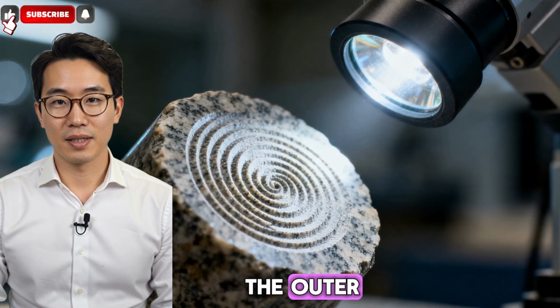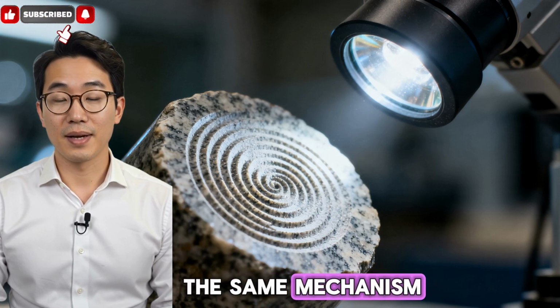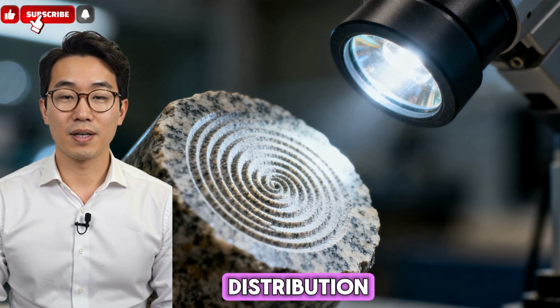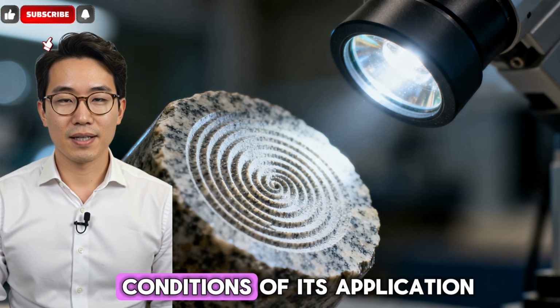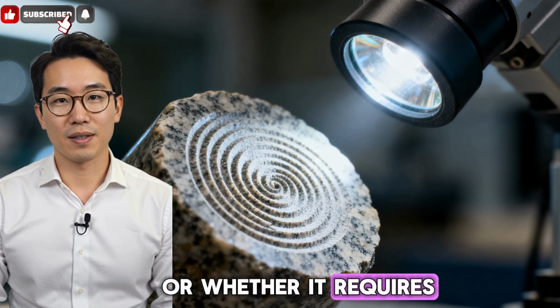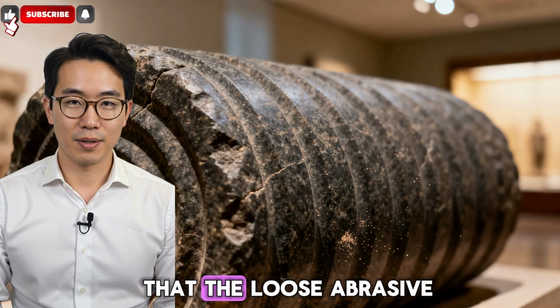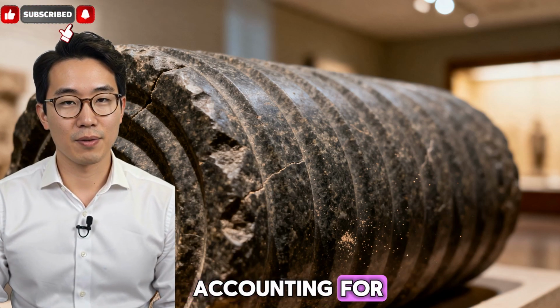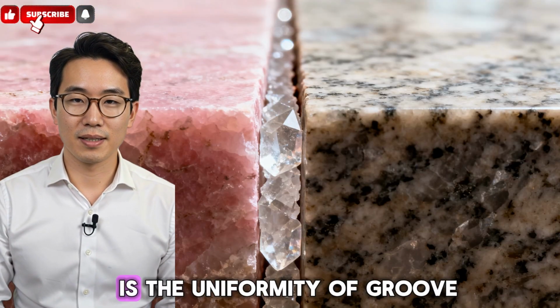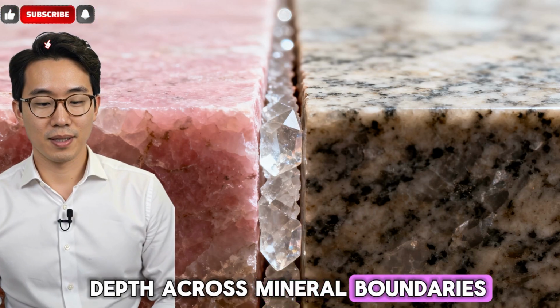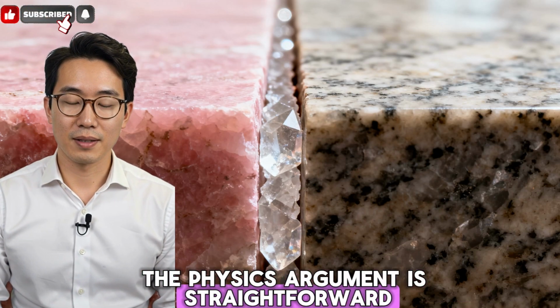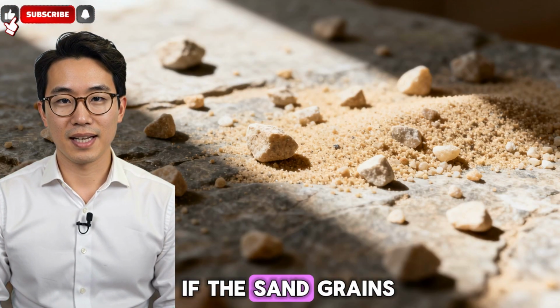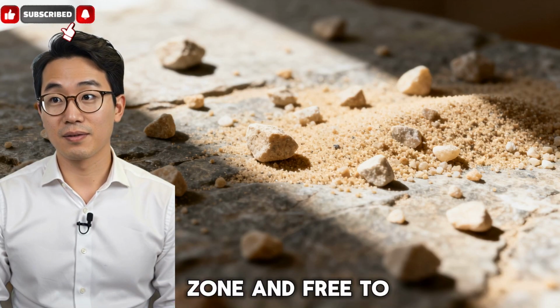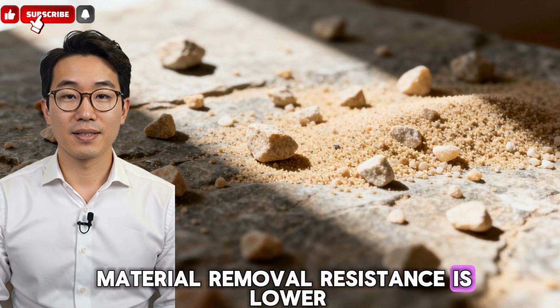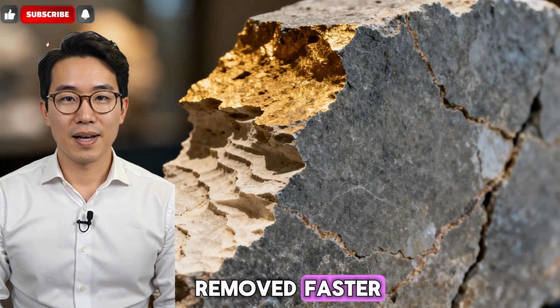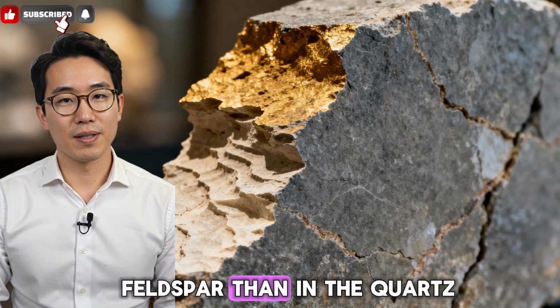The question is whether the outer edge of the distribution can be explained by the same mechanism that explains the center of the distribution, by invoking variations in the specific conditions of its application, or whether it requires an additional mechanism. The key variable that the loose abrasive mechanism has difficulty accounting for in the anomalous cores is the uniformity of groove depth across mineral boundaries. The physics argument is straightforward. If the abrasive is loose, if the sand grains are distributed randomly in the contact zone and free to concentrate where the material removal resistance is lower, then the softer minerals will be removed faster, and the groove will be deeper in the feldspar than in the quartz.